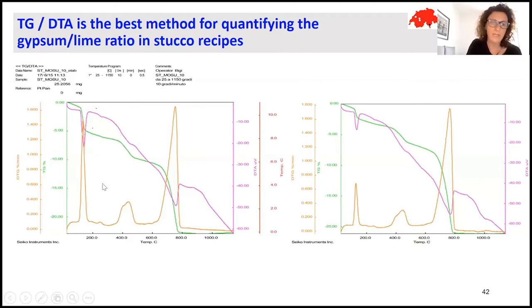For example, if we see this pattern, we see that around 120 degrees we have the weight loss of gypsum. Then we have the magnesium component here around 500 degrees, and then we have the lime and the calcite weight loss around 700 degrees. By making a simple proportion, we can get the different amounts of these components.